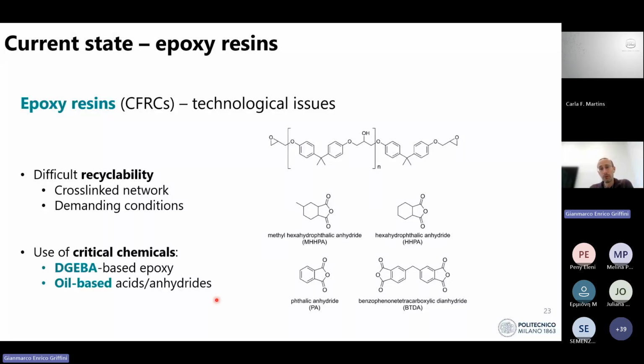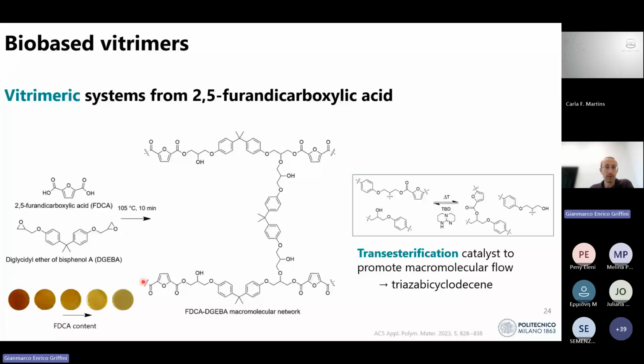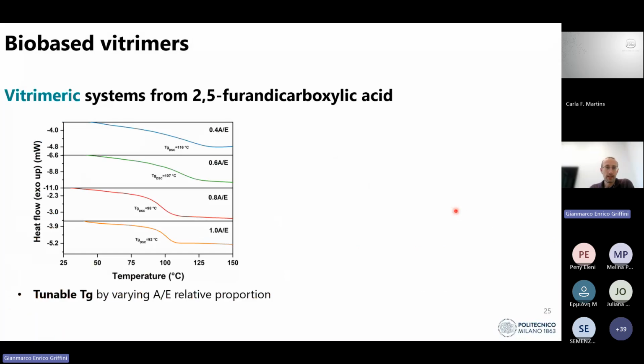So what we did there was to, first of all, focus on the anhydride or the acid cross-linker by substituting conventional ones with FDCA, furandicarboxylic acid. By developing this system and by modulating the formulation, we could obtain a three-dimensional network that is actually a fully cross-linked epoxy system. And through the introduction of a transesterification catalyst, triazabicyclodecene, we could potentially envisage their reversibility thanks to the transesterification reactions that can occur at relatively moderate temperatures, let's say.